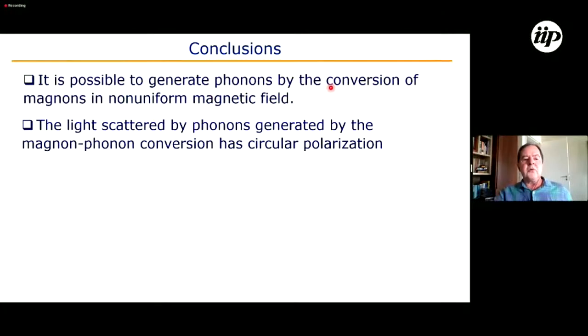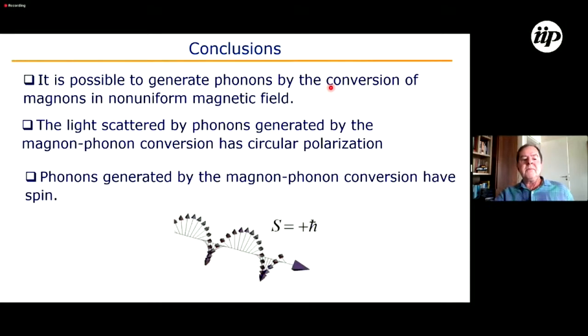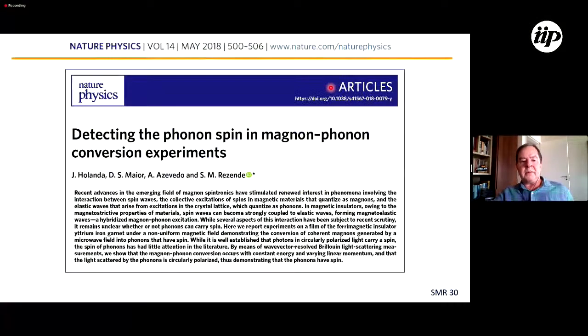So these are the conclusions of this topic. It's possible to generate phonons by the conversion of magnons in a non-uniform magnetic field. The light scattered by phonons generated by the magnon-phonon conversion is circularly polarized. So phonons generated by the magnon-phonon conversion have a spin, and they have plus or minus h bar angular momentum. These experiments were published in Nature Physics almost 4 years ago.